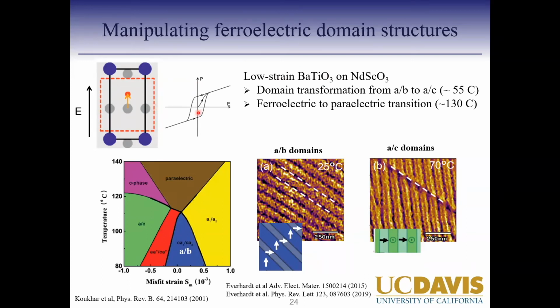And that polarization, as a function of electric field, you can control, and that results in a hysteresis loop, very similar to how you have a ferromagnetic material under applied field, where you control the spins. In this case, you control the polarization, which means this titanium atom is shifting from up all the way down. So this is happening because of structural distortions. For these domains, we're not used to thinking about whether they will actually fluctuate. So that's what we're going to talk about in the second half of this talk.